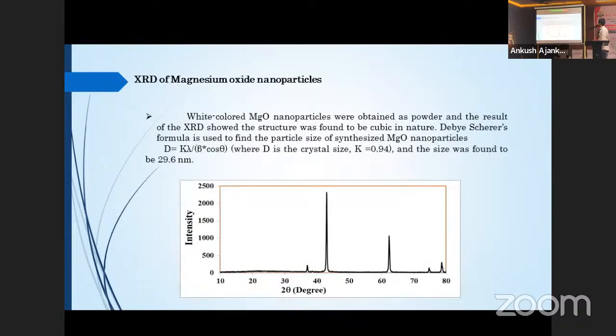This is the XRD pattern of the magnesium oxide nanoparticles. White colored powder nanoparticles were obtained, and the structure was found to be simple cubic, using the Debye-Scherrer formula. The formula is D equals K lambda upon beta cos theta. The average crystal size found is 29.6 nanometers, which confirms the particles as nanoparticles.